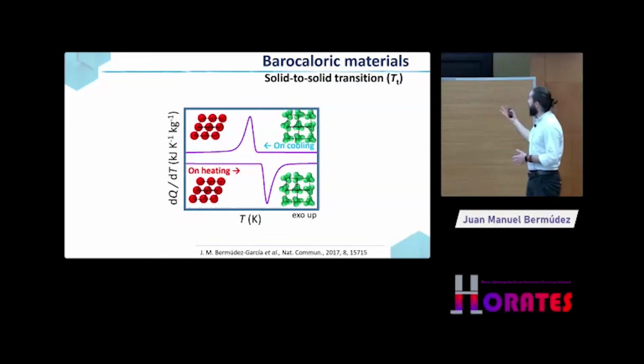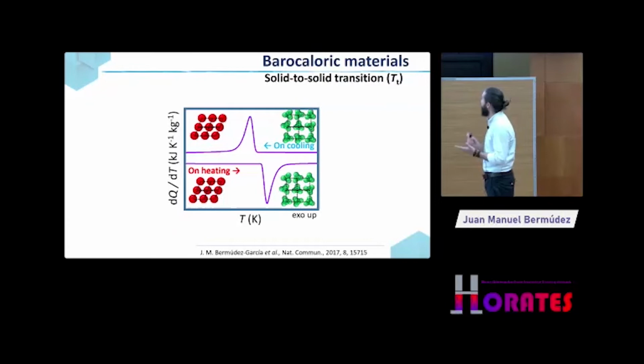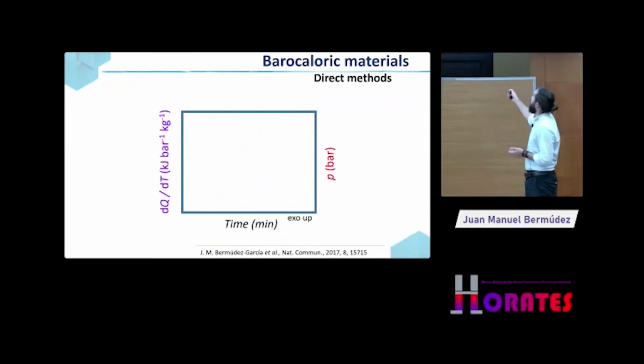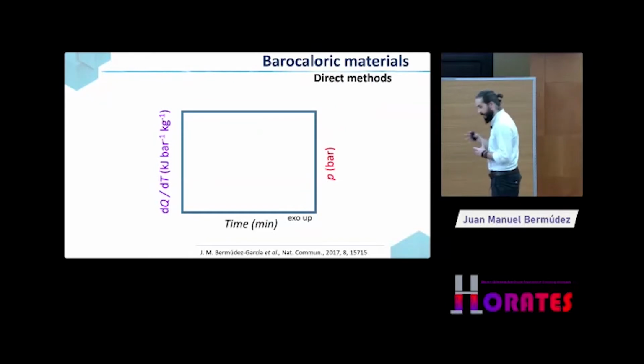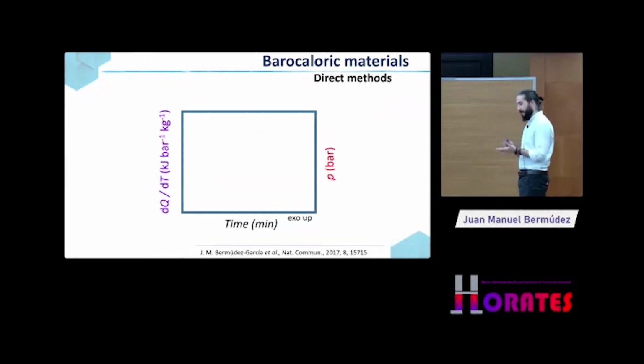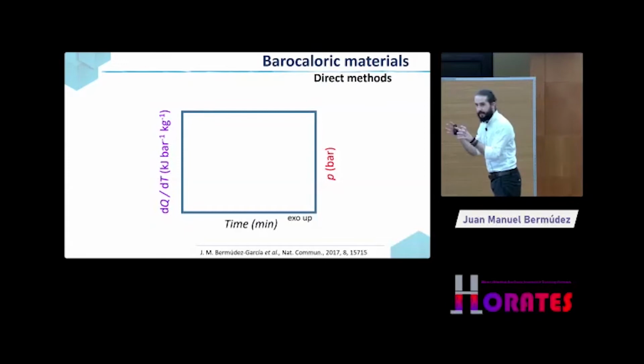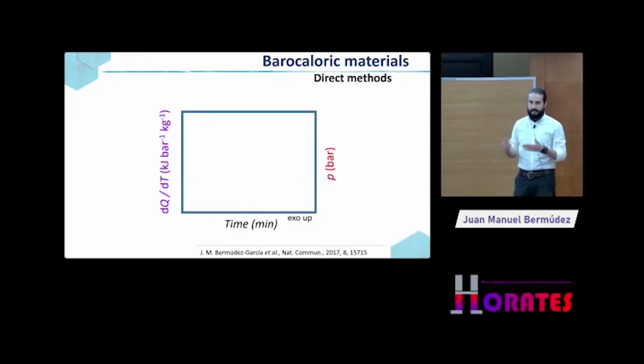But then you play with the pressure, and there are two main methods that you can use to obtain data from differential scanning calorimetry under pressure. So the first type of methods are called direct methods, and they are less common because it is really difficult to find a laboratory in the world that can have this kind of calorimeters. So you have a calorimeter that can not only do ramps in temperature, but they are coupled with a pressure cell, and this pressure cell is able to first fix an isothermal condition at a given temperature, and then the cell can increase and decrease the pressure in a controlled way, right?